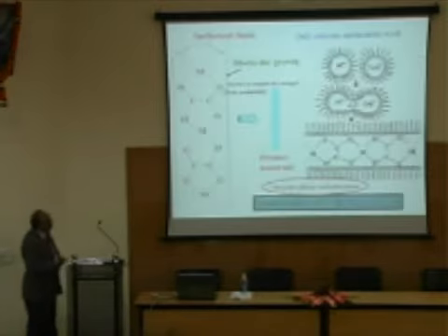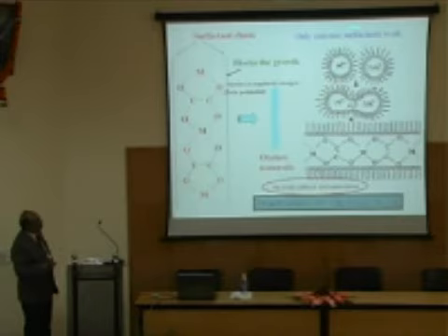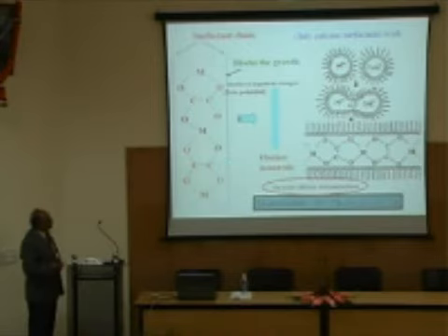So this is a typical case of making rods of some metal carboxylates. So we have a microemulsion based on a cationic surfactant, and these rods are aligned because the surface of this rod, because of these oxygens, becomes negatively charged, and these cation surfactants have a positively charged head group which blocks the growth of the rod in this direction.